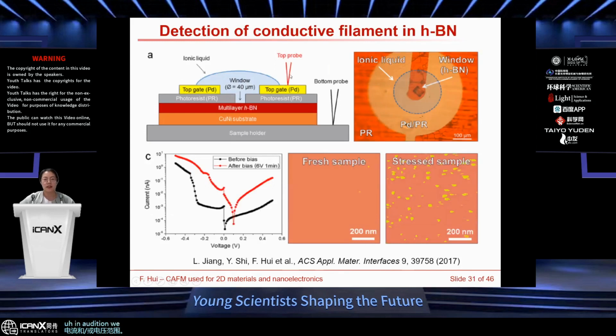In addition, we can also detect the conductive filaments in two-dimensional materials, or the switching or active layer in memristors. In this work, we first stress this device at the nanoscale at the device level, and then we remove the ionic liquid. Then the underlying multilayer hexagonal boron nitride was exposed. Then we use the C-AFM to scan this tiny area, and we can observe the dimensions and the distribution of the current conductive filaments.